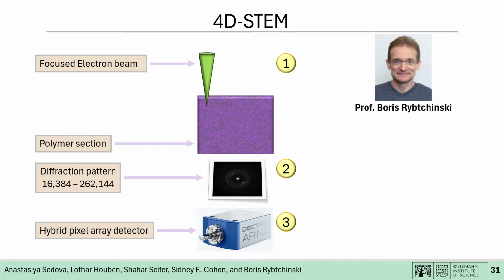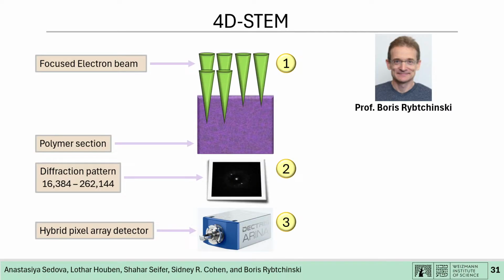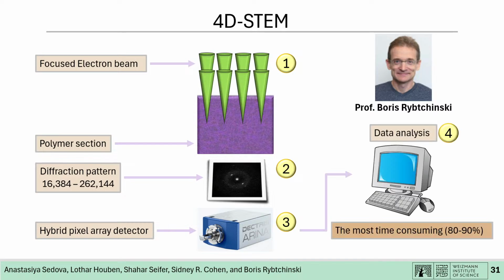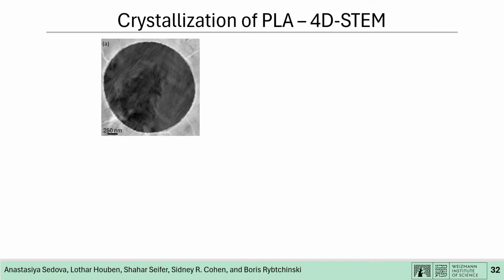So the technique is developed in a transmission electron microscope. We have a focused electron beam that scans the sample, and we can collect a diffraction pattern at each scan position. We have a high-speed detector, and we can collect as many as 16,384 to 262,144 diffraction patterns. Those patterns we can analyze by computational means, and this is the most time-consuming process. So what can we study from this information?